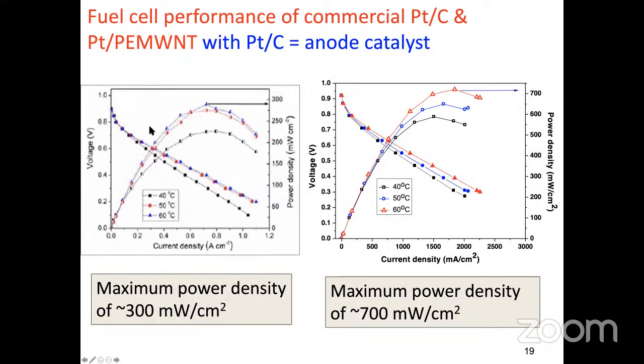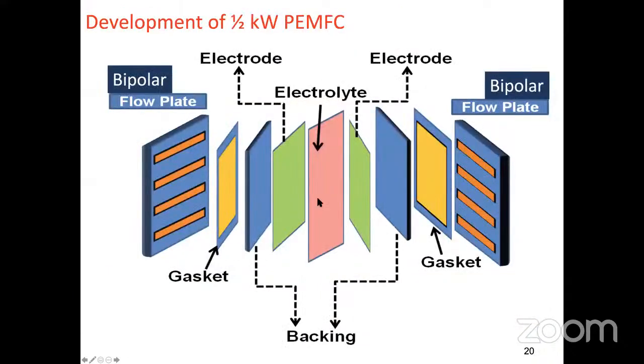So the performance of this commercial catalyst, this is the voltage, and this is the current density, this is the power density. You can see that very close to 300 milliwatt per centimeter square. But what is the performance with reference to our material is that you can see that we will get almost 700 milliwatt per centimeter square, 2.5 times increase with reference to the performance, because of the use of carbon nanotube or graphene as a support material, which are nanomaterials, and then platinum is also almost 5 nanometer crystalline. And once we have done this, so it's a single cell.